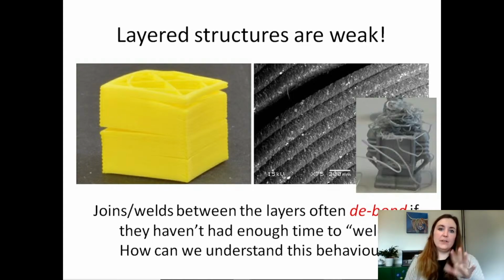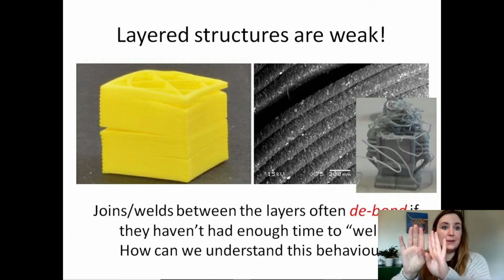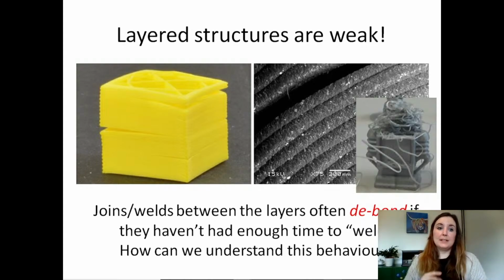And it turns out even if your weld visually looks okay, it's usually much weaker than what you would expect from your plastic properties. And you can measure this weld strength. If experiments are your thing, you can do a mechanical test and tear along these weld lines and measure a tear energy. And this is always much weaker than what you would expect from the bulk properties of your plastic. So this is a real problem for 3D printed products.